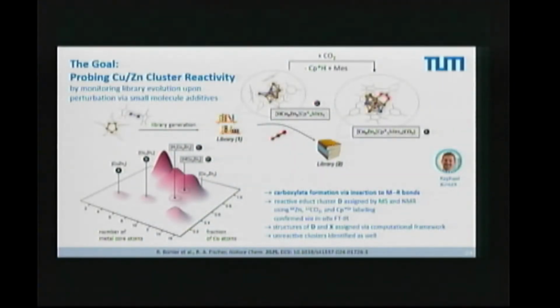And we are convinced that it's reasonable to believe that this structure is true, because we have a growing list of the ones we can isolate and calibrate against. The list of good fits is getting larger and larger and larger. So we are very convinced that for the ones we cannot access experimentally, we have a good guess of the potential structure. Now, how does this come together in probing reactivity?